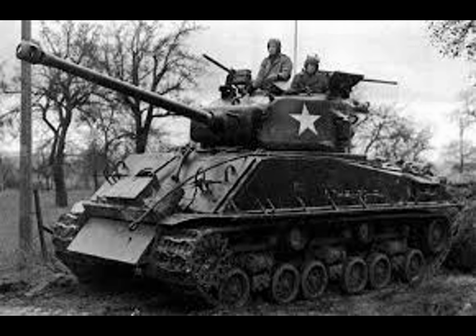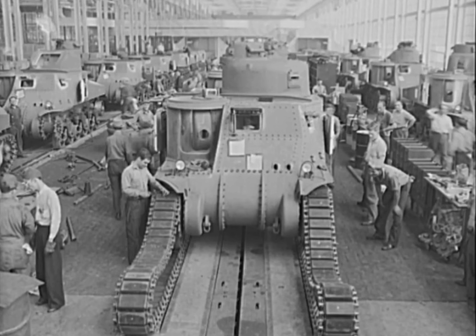The process began with electric arc furnaces that melted scrap steel and alloying elements into precise compositions. For armor plate, specifications called for 0.35 to 0.45% carbon, 0.8 to 1.2% chromium, and 0.15 to 0.3% molybdenum. Manganese, silicon, and trace elements rounded out the composition. Each heat, typically 200 tons of molten steel, underwent spectrographic analysis before pouring. If composition fell outside specifications, the heat was adjusted by adding alloying elements or diluted with low alloy steel. This quality control happened before any steel solidified into ingots.